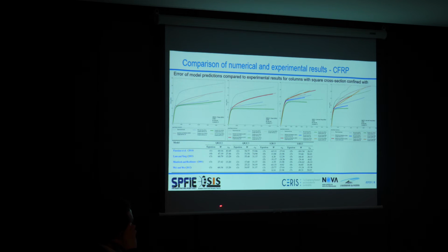And that can be seen, for example, when we see the strain energy density. Okay, what is this? This is the area between the stress and the strain. It's the area of the graphic, and we can see that we have high values. For example, some are about 60% error regarding the strain energy density. And when we look at the value for the rupture of the fiber, you can see that in equation 3 we have the smallest value, about 30.3% of error.